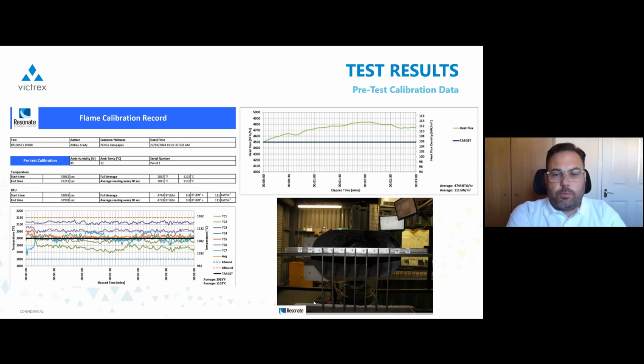So this is what we call the pre-test calibration data. If you remember, we said that before you start any test, you do the calibration. On the left, what you see is the temperature of the 9 type K thermocouples, and they have to be within a certain range, and obviously their average has to be 1100 degrees C or 2000 Fahrenheit. And you can see there on the lower right how the thermocouples are placed. Again, the position and distance of the thermocouples, everything is set in the standard. So you have to adhere to the standard. Also, the type of thermocouples and how you calibrate them, everything is part of the test standard.